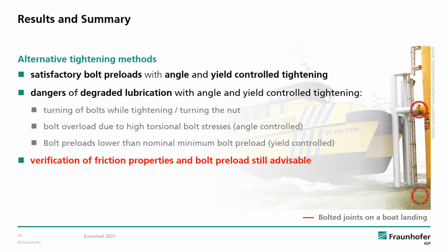Still, degraded lubrication is not desirable with angle or yield-controlled tightening either. In case friction gets too high, there is a danger of bolts turning while being tightened if not secured properly, which would lead to misleading tightening results and preload lower than expected. In case friction is even higher, angle-controlled tightening might lead to bolt overload due to high torsional bolt stresses. With yield-controlled tightening, friction this high could lead to the tightening process being stopped early and before minimum bolt preload is reached. We've actually seen all of these things happen with bolt size M16.